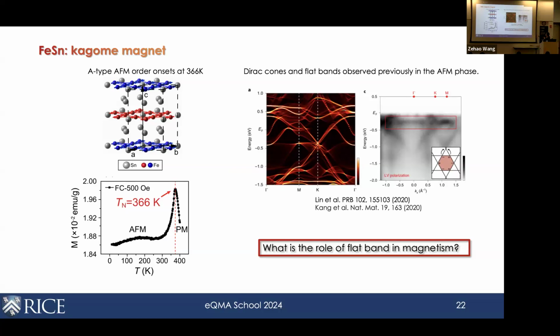And you can see that in this work by the MIT group, they've already identified the key signatures of the Kagome electronic structure, including Dirac crossings, Dirac points and flat bands. But because of this extremely high ordering temperature, this makes the single crystal studies very difficult for ARPES to actually look at the evolution of the electronic structure across that temperature, because the sample usually dies in vacuum before you reach there. So ultimately, we want to understand, does the flat band play any role in inducing the magnetic order here?